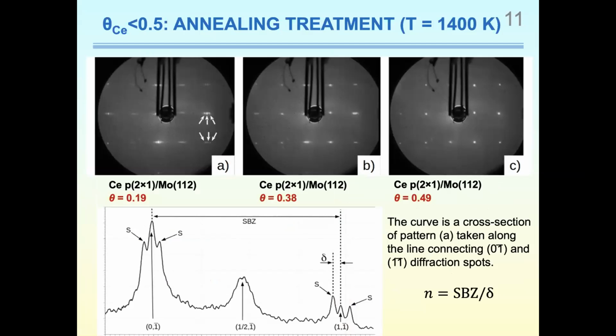Another significant result of annealing for coverages less than 0.5 was revealed in the range of annealing temperatures greater than 1200 Kelvin. Satellites appear on both sides of integer order LEED spots, as indicated by arrows. Notice that the half-integer order spots continue to exist. According to the literature, features of this kind reflect the emergence of some mesoscopic superperiodicity on the surface. In our particular case, this is one-dimensional periodicity along the 1,1,-1 direction within the primitive 2x1 structure. Judging from the delta value, the satellite splitting relative to the integer order spots, the mesoscopic period N amounts to about 24 substrate lattice units, which is about 65.5 angstrom.